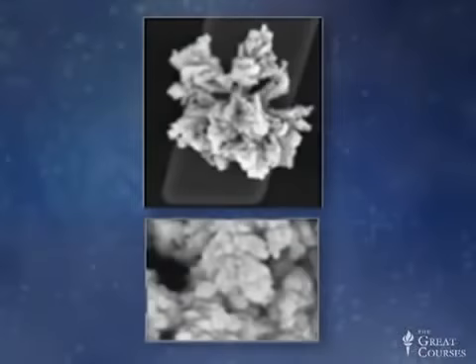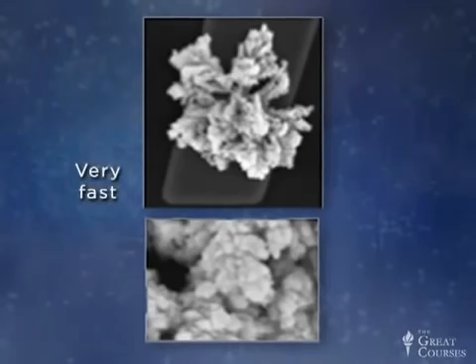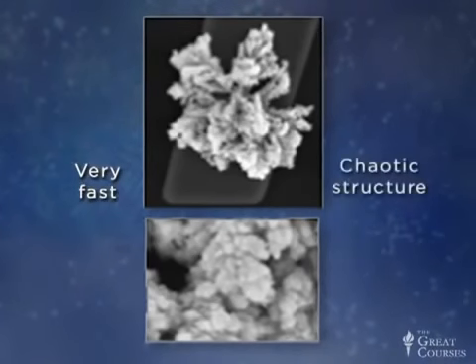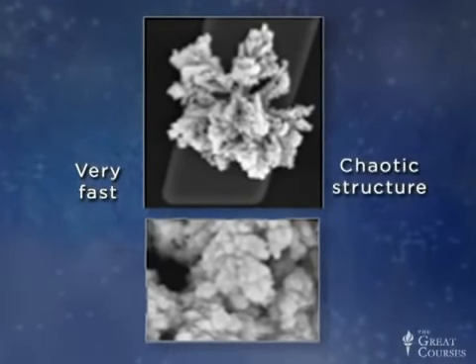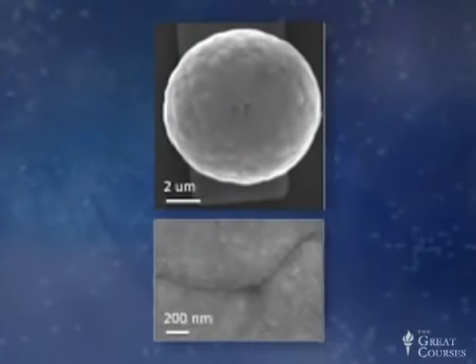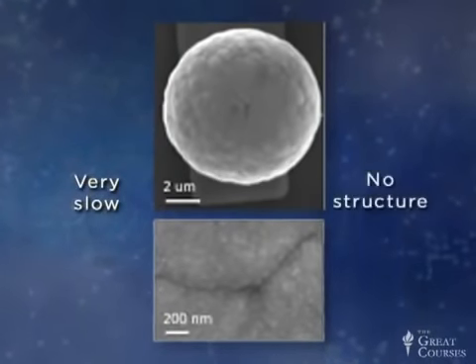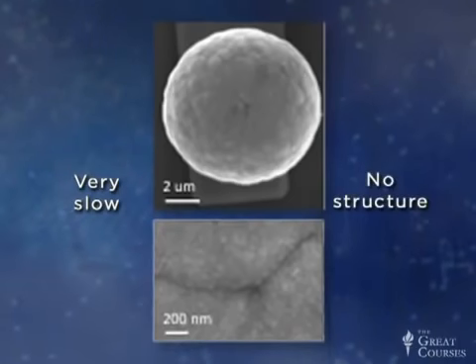So why do these different levels of nanostructuring appear? We actually use the same materials to make them, same conditions in solution, except for one condition, and that has to do with how fast we do the electroplating process. If we make it go very fast, the metal plates onto the chip very chaotically, and the voids formed in the sensors don't get filled in. If we go slowly, we don't get any nanostructures because all of the voids are filled. So you get this nice, smooth sensor. So this is a nice, easy way to control nanostructuring.